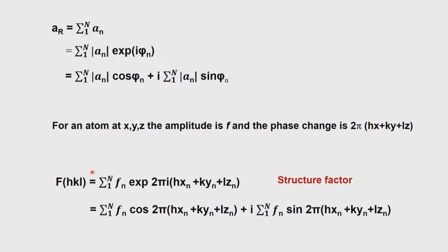You see that there is no modulus written here. So, it is the actual structure factor, modulus and the phase together, and this is the expression we need to put into the Fourier transform expression of rho of r, so that we can get to the rho of r. So, this is the value which we need to compute electron density. This structure factor can also be written conveniently in this form, cosine plus i sine.